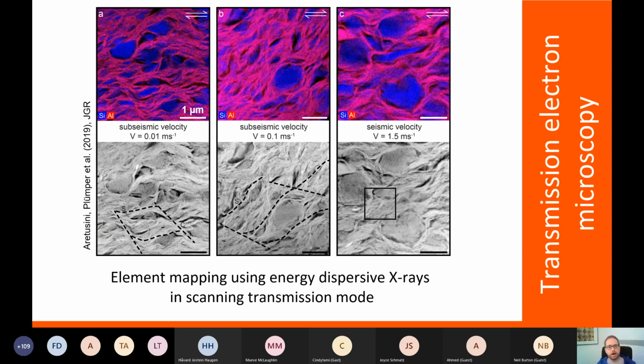So now that we can scan across our sample, we can also produce element maps using X-rays. Again, we will talk about this in the next lecture, but you can do element mapping at very high resolutions. In this case, for example, it was a study on deformed quartz clay mixtures, seeing where the clay wraps around the quartz. You can map this out very nicely in a TEM on a focused ion beam sample.